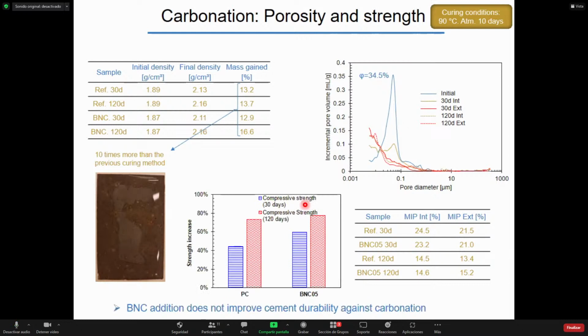In contrast with the previous curing method, we saw in this case strength increases inside the cell, probably due to the hydration process that is still taking place in the carbonation cell at the same time as the carbonation. So in this case, bacterial nanocellulose does not improve cement durability against carbonation.